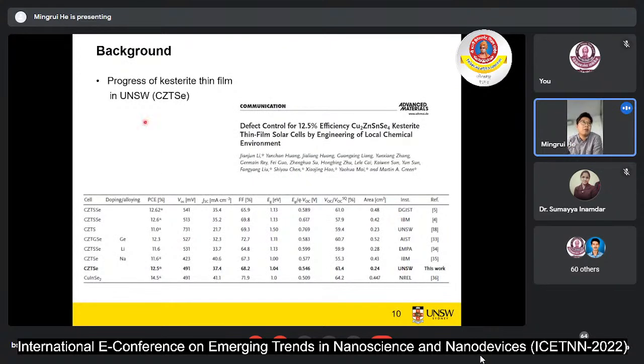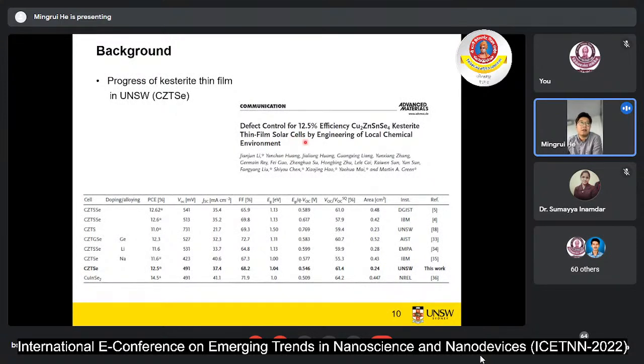Another one is we also did a little bit of research on the pure selenide CZTSe. We achieved a certified efficiency around 12.5% in 2020. Here we can see we almost achieve the same VOC value compared with copper indium selenide, and we also get the lowest VOC deficit. The low VOC deficit is a key issue for the kesterite materials. So we did a pretty good job in both materials.